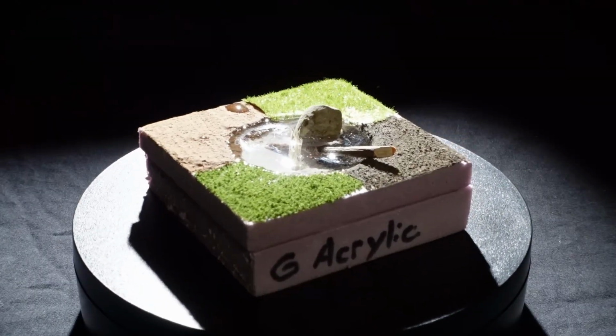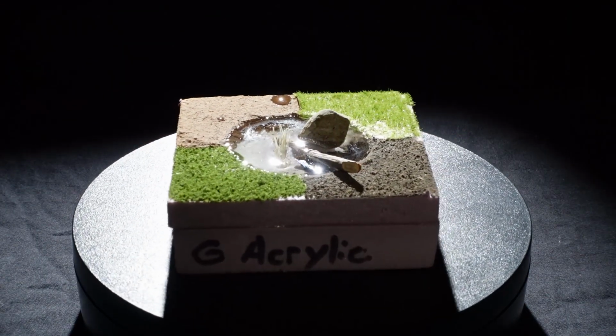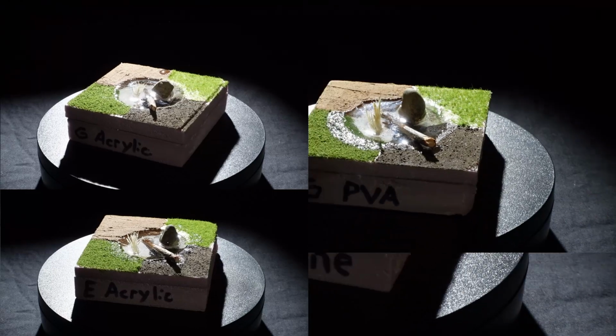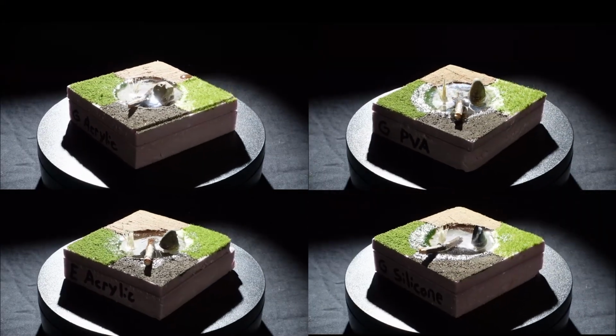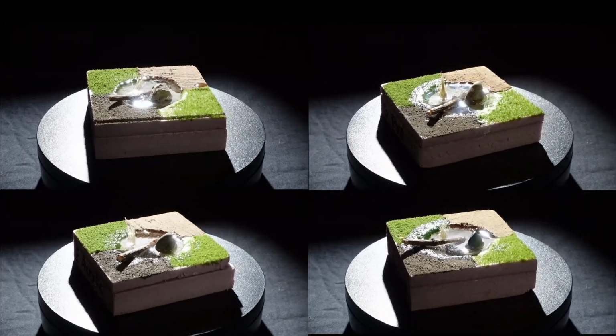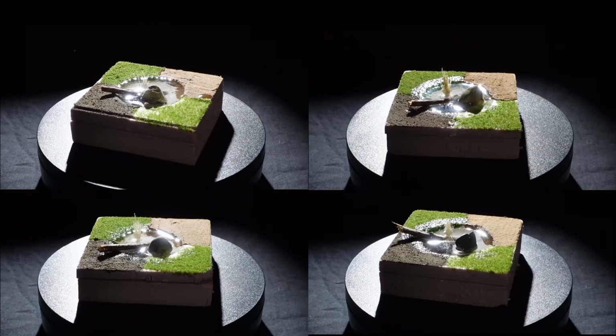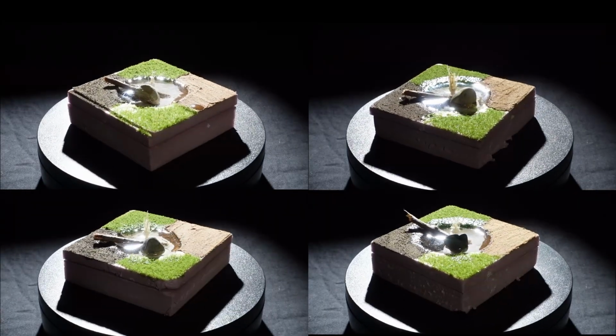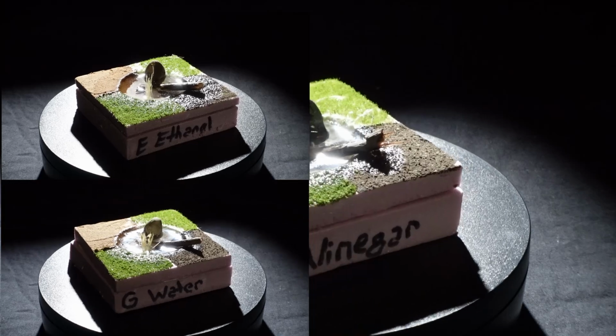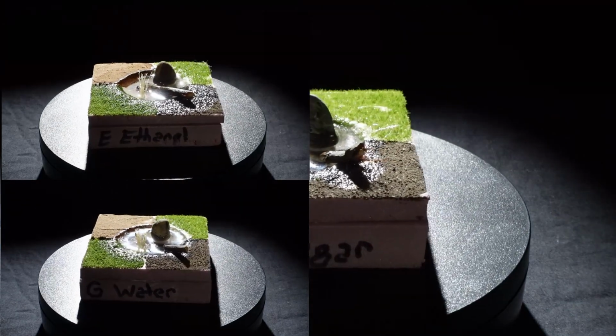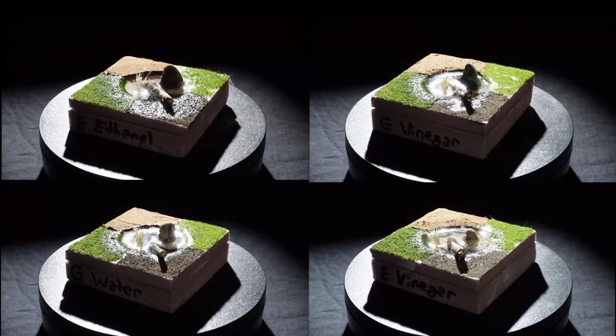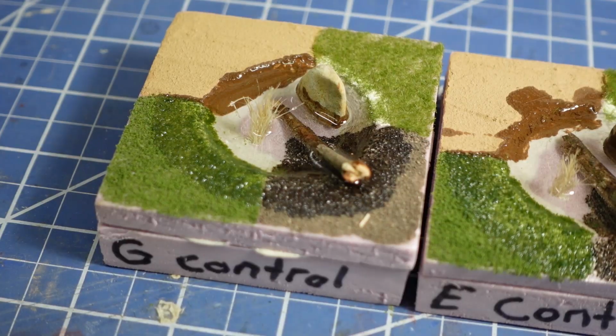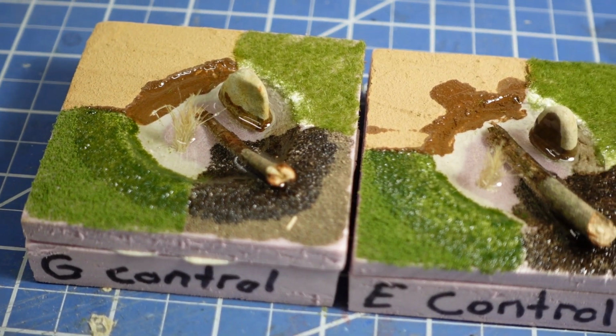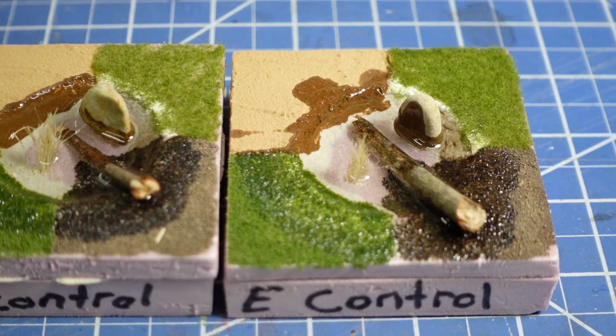In conclusion, nothing completely eliminated the meniscus, but acrylic, PVA, and silicone lubricant did a pretty good job of reducing it and preventing creep into the scenic materials, which is good news as acrylic paint and PVA glue are pretty common scenic materials. Ethanol and water produced no improvement or even degradation, and vinegar made no improvement while damaging the scenic materials. There was no difference I could detect between the name brand Envirotex and the generic epoxy resin.